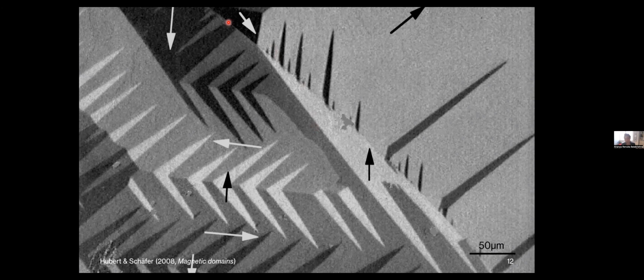You see them at grain boundaries, and you see them near the edges and sharp corners. And here is a really nice book by experimentalists Hubert and Schaefer, who have developed very sophisticated microscopy techniques where they map these domains. If you flip through this book, you'll notice several of these needle domains surfacing in the micrographs, indicating that these are commonly observed across several of them.